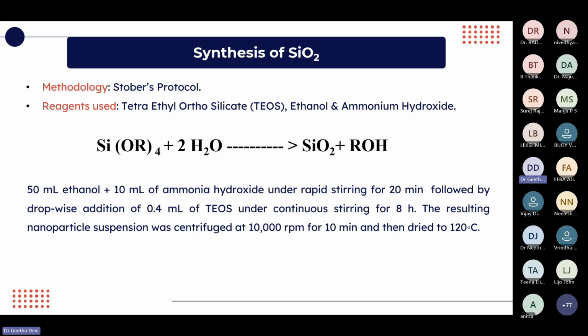The reaction is carried out by mixing 50 ml of ethanol, 10 ml of ammonium hydroxide with rapid stirring for 20 minutes. And this was followed by 0.4 ml of tetraethyl orthosilicate, and the reaction was carried out up to 8 hours. After 8 hours, the resulting nanoparticle suspension was centrifuged at 10,000 rpm for 10 minutes and then dried at 120 degrees Celsius to make a fine powder. The dried form of the powder was used for the characterization and analysis.